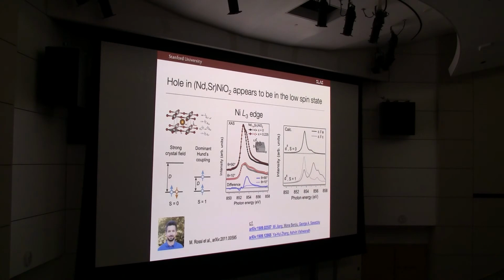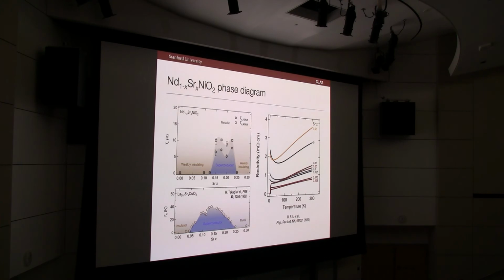If we hole dope or pull one of them out, you may think that we're just going to pull out this top electron, but actually it's possible that you'd rather pull out this lower electron. The reason is that you have this strong on-site Hund's rule coupling to minimize exchange effects. So it's a function of the level splitting versus this coupling, which wins. To make a long story short, by looking at the X-ray absorption spectra on the nickel L edge, the story seems to be consistent with the low spin state. Okay? So let me tell you a little bit about the phase diagram.